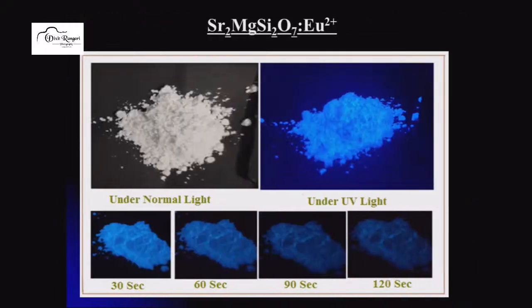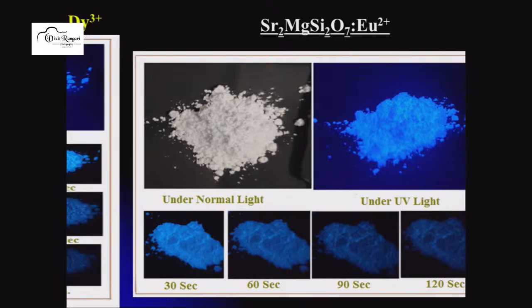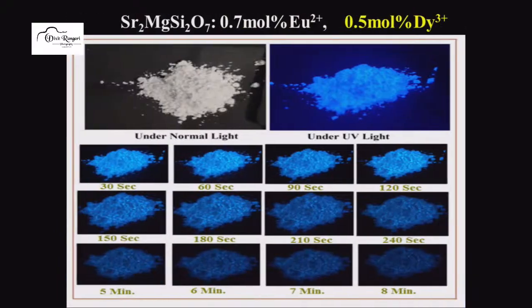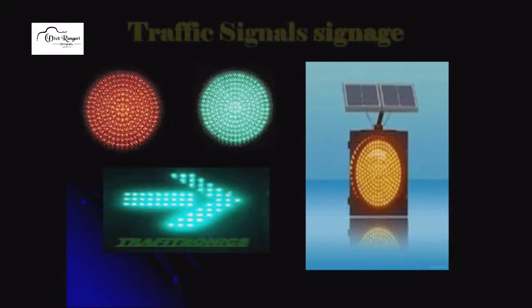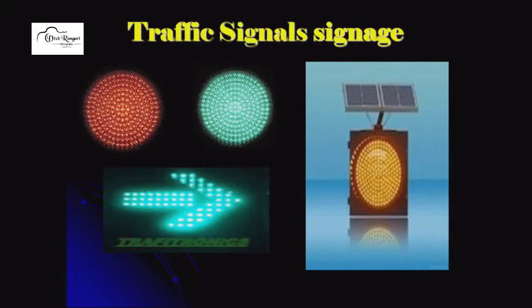So this is strontium magnesium silicate. The decay time is only up to 120 seconds. But you can dope this material with Eu2+. You can co-dope with Dy3+. Then the decay time increases up to 8 minutes. So correspondingly the efficiency is again increasing, and this is useful for road safety, like this type of signal.